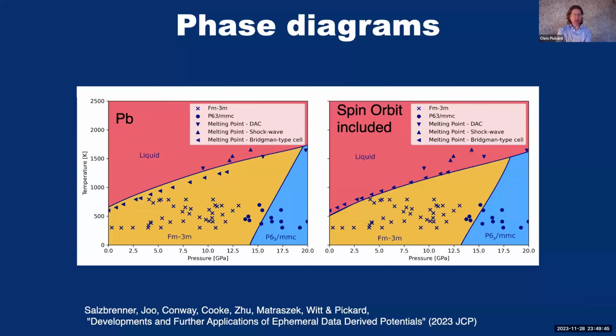So this is an example of a phase diagram computed by Pascal Salzbrenner, a PhD student in my group, where he was able to develop a potential for lead, including spin orbit, to do calculations, including, now here we've got melting lines, including coexistence melting, that are simply not possible from a first principles point of view. You can't converge these spin orbit metallic calculations to a level of accuracy in large enough unit cells where you can actually run long enough coexistence and molecular dynamics simulations.